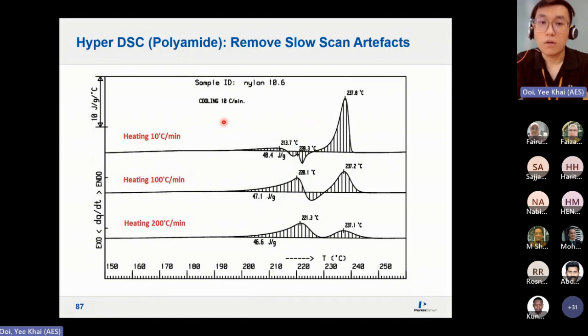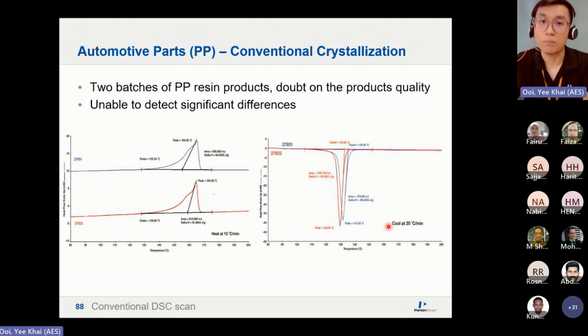So like what I mentioned just now, for semi-crystalline material, if you heat up at a normal heating rate, it's going to recrystallize and then melt. But if you heat up very, very fast, you can suppress the recrystallization. So the material wouldn't have time to recrystallize and then it will melt. So this is the true nature of your material, because in real life, your end product doesn't segregate or recrystallize into different forms. It should just melt with the heating rates that we are supplying. So usually only a high heating rate can suppress this, and it will reflect the true nature of your end products.